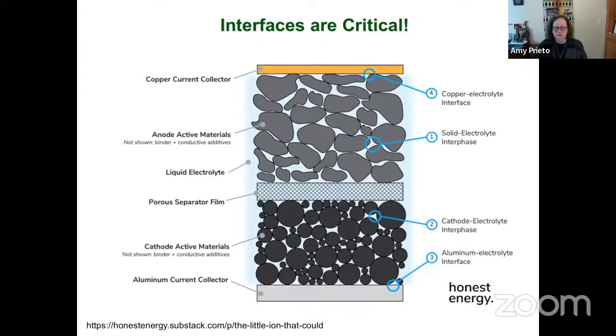So if I zoom into any one of those architectures I just showed you, the picture becomes more complex. In this case, I'm showing you a copper current collector on the top, some anode that is, say, graphite or graphite mixed with silicon with binders, conductive additives. There's some distribution of morphology and particle sizes. And so at every one of those interfaces, reactions can occur. Then we have our porous separator, say, liquid soaking the whole battery, and then on the bottom, a cathode material, which again is typically particulates that are combined with binders, conductive additives, and again, pretty high surface area.